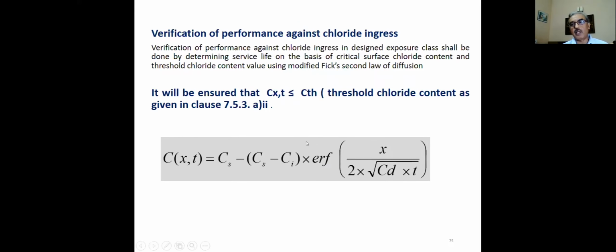But in case of chloride attack, the limit state is taken as the time by which the threshold value is reached. We don't wait for the crack. So when that threshold value of chloride is reached at the surface of the reinforcement, we consider that as the limit state here.